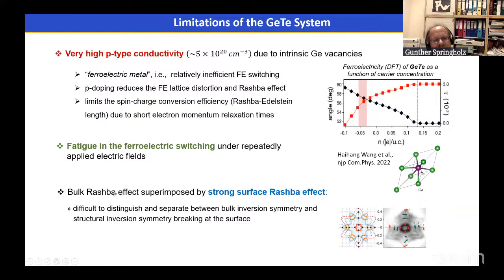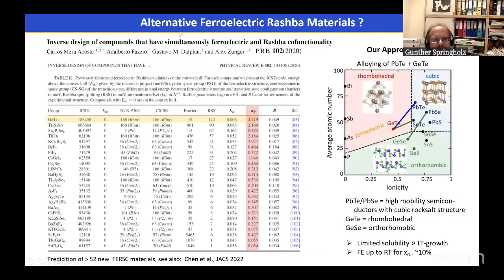Another effect that I mentioned is that in germanium telluride we have these strong surface bands appearing on the surface of the material. So we have a bulk Rashba effect superimposed by a strong surface Rashba effect, and that is always difficult to separate between these two different contributions experimentally. So we have looked for alternative ferroelectric Rashba materials.